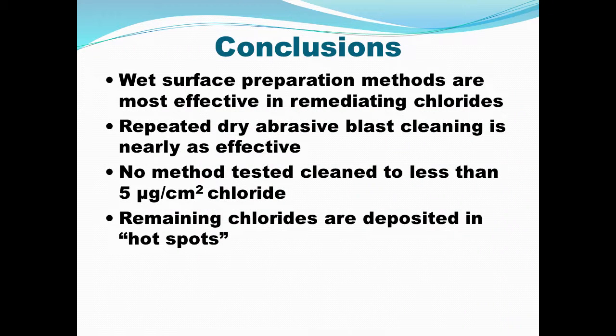So our conclusion from this, first of all, our recommendation to the cabinet was, unless you want to start employing wet methods and dry methods together, which complicates your waste handling or your residue handling, and makes longer time on the project, the best thing you can do at this time is blast to an SP10, let it flash, and blast it again. That's not new. People have found that 20 years ago, probably, and we just reproved it for the Kentucky Transportation Cabinet.